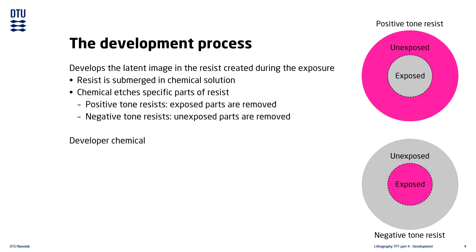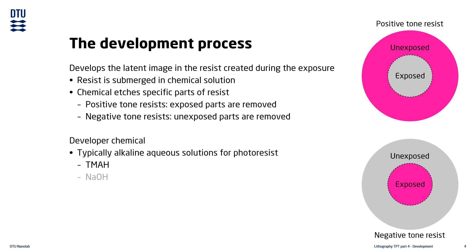Photoresists are typically developed using aqueous alkaline solutions. Two very commonly used chemicals are TMAH and sodium hydroxide. E-beam resists are typically developed using solvents, and a commonly used solvent is pentyl acetate.